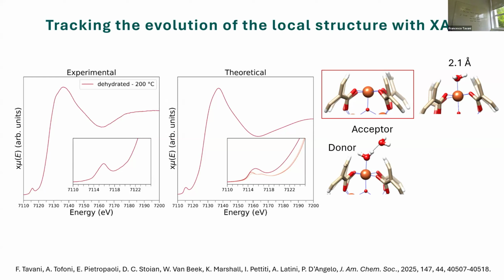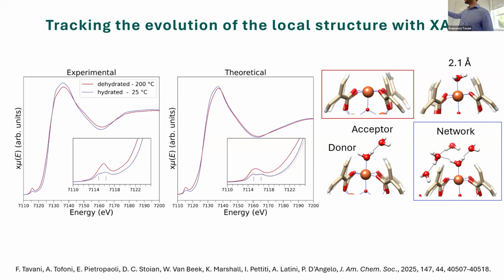And you can see that the intensity of these two peaks in the pre-edge region starts to change. We were able to attribute this to the existence of hydrogen bonding between the water molecule directly coordinated to the metal sites and, let's say, the second sphere water molecules. This progressively leads to a network, and at the higher water molecule loading, we recover the experimental pre-edge intensity ratio quite well. This for XAS, by the way, is considered excellent agreement since we are not doing fitting. Let's say this was a very exciting result for us.